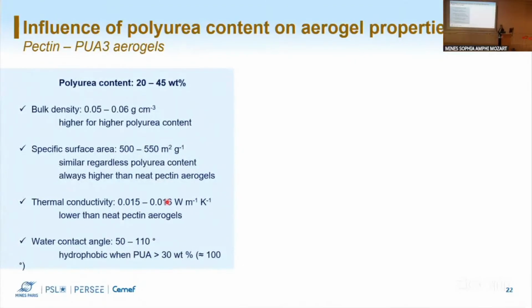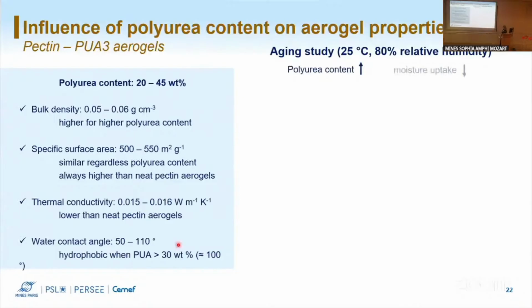We saw that the variation of polyurea content didn't really affect the bulk density, surface area, or thermal conductivity, but we had an effect on contact angle. So the materials were hydrophobic only when polyurea was more than 30% inside the material. We did aging studies in the same conditions as before, at 25 degrees and 80% relative humidity. When polyurea content was increasing, moisture uptake was decreasing and the bulk density increase was lower.